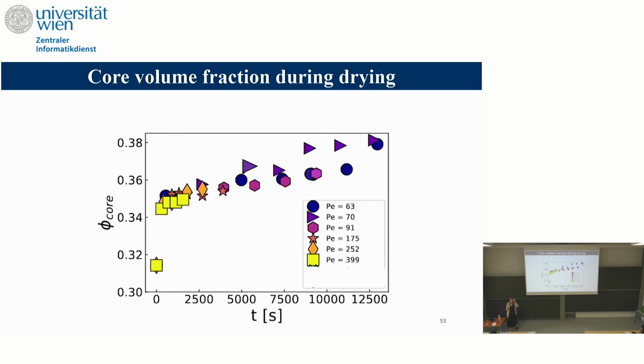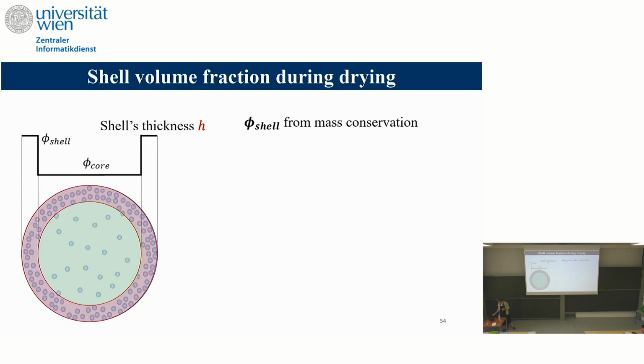This is an experimental observation. You increase the volume fraction even in the core of your particles. It's not constant, and we think particles get stuck at the boundaries. Then we do something quite bold, because it probably does not reflect the reality: we assume a step function. We have the volume fraction in the core, and a shell with a step function with a thickness h.